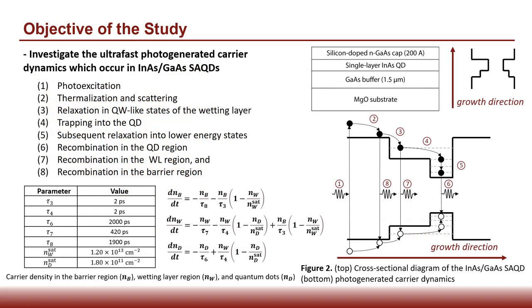In this study, I plan to investigate the ultra-fast photogenerated carrier dynamics which occur in an indium arsenide / gallium arsenide self-assembled quantum dot system. The carrier dynamics are indicated in the band diagram on the right-hand side and are also modeled by a set of coupled differential rate equations shown below.